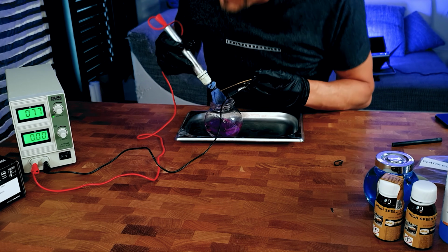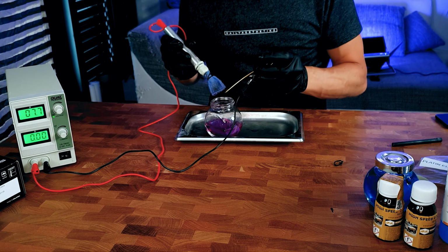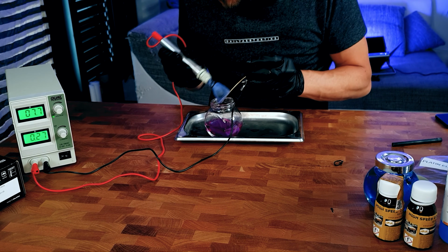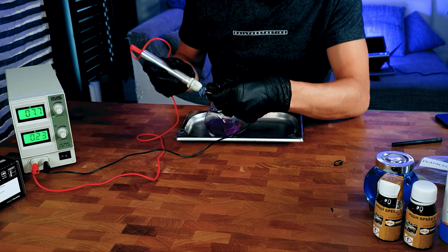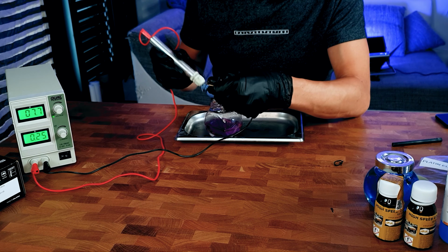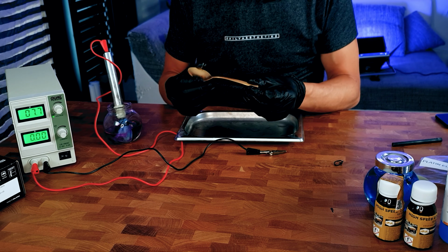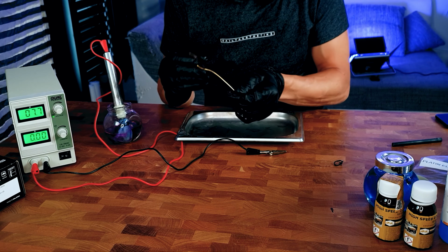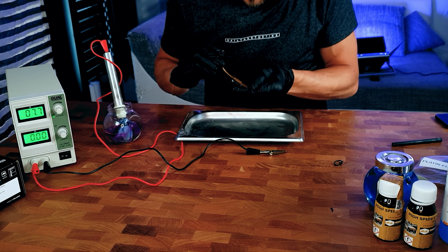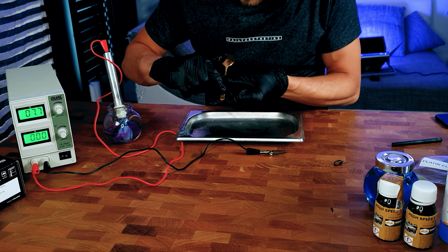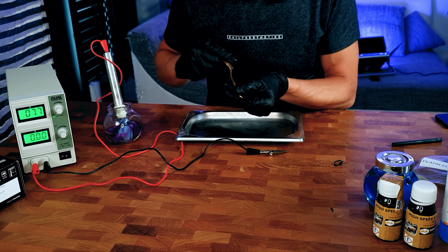So I've gone up to 7.7 volts now. The more electricity you put through, the thicker your gold will get. Don't overdo it though, it will get burned. After you're done with electroplating, just try to rub off the gold to see if it's thick everywhere, or if you have some spots like here where you have to clean again and maybe replate.